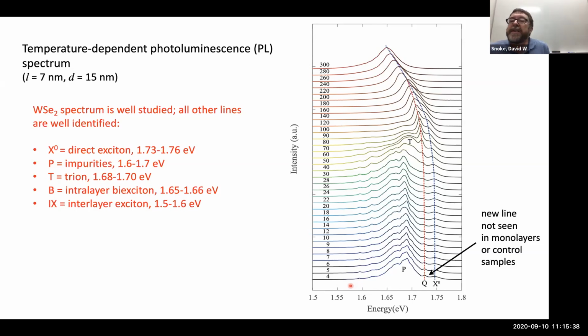And that is well separated in energy. It has a very different lifetime. It's a very long lifetime because there has to be tunneling between the 2 layers for it to emit. And so it's easy to identify.